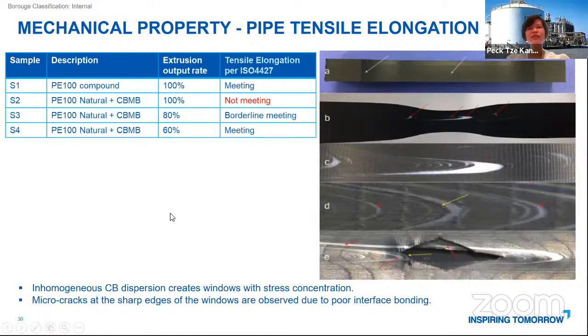As we know, there is a very poor distribution of carbon black, creating this white area and black area. The black area actually has more carbon black concentration. So there is a stress point here. The stress points are the initiators of the failure, which occurs much earlier than a normal tensile performance. So this is why we find it very difficult to meet the tensile elongation if we do a salt and pepper mixing to produce the pipe.